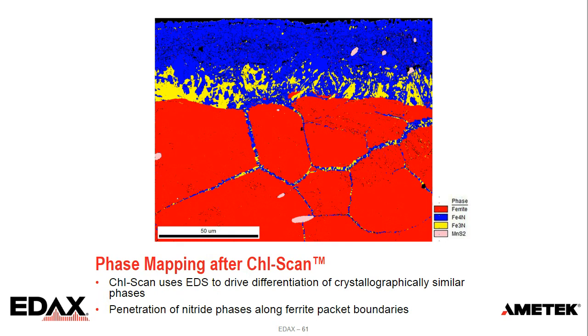From that, we can differentiate better the crystallographically similar phases. We can see the true phase distribution. And then we can also start to see how the nitride phases are present on the outer layer, as well as how they're penetrating into the microstructure through the ferritic packet boundaries. And so we can see that in terms of the comparison before and after ChI-Scan.